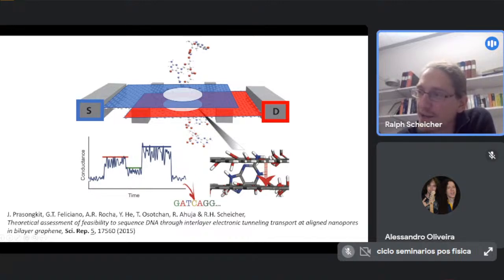And so one can analyze then the conductance signal from the source to the drain electrode as a function of time. And the hypothesis here is that different levels of conductance correspond to different bases. So from the magnitude of the conductance, you can maybe deduce the base nature. Or you can also, in addition, take into account how long a base needs to propagate through these graphene nanopores. Some of them take longer, some of them take shorter. That depends on the interaction strength. How strongly are they binding to these graphene nanopore edges, basically? So you have 2 sources of information here, the magnitude of the signal and the duration of the signal.